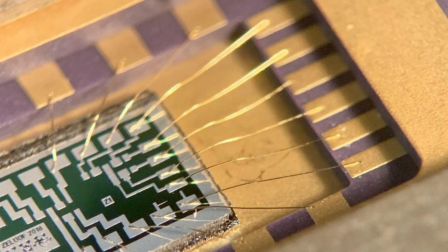In the real labs and industry they want to avoid depositing such thick films over one or two microns because it takes a long time and a lot of material in the vacuum. So they normally do electroless plating of say nickel and thick soft gold on top which also makes a very reliable bond. Often times these platings can be as thick as four to ten microns and it's a lot easier for them to bond wires to it that way.